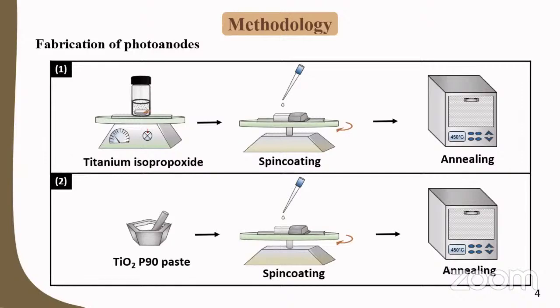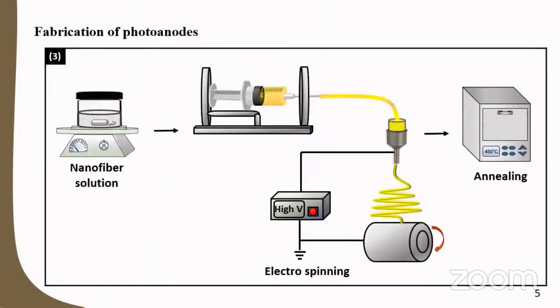The above substrate with the compact layer was then covered with the paste prepared from TiO2 P90. For that, 0.25 gram of TiO2 P90 powder was ground well with 1 milliliter of 0.1 M nitric acid. The paste was spin coated on the TiO2 compact layer at 3000 rpm for 1 minute and similarly sintered at 450 degrees Celsius for 45 minutes. This is the modified layer of the photoanode.